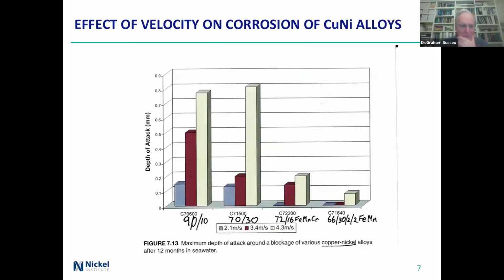This is some data looking at the maximum depth of attack around a blockage in various copper nickel alloy pipes in 12 months in seawater. On the left, we've got 90-10, and the grey thing is with velocity of 2.1 meters per second. The 3.4 meters per second is the red, and the pale yellow, whatever it is, is at 4.3 meters per second. Now that's getting pretty fast for a copper nickel. For a stainless steel, it's absolutely nothing. But the difference is in terms of what gets swept away in terms of the copper, so that it doesn't actually stop the depth of attack going on. Notice that the attack depths there are up to 1 millimeter, not very much.